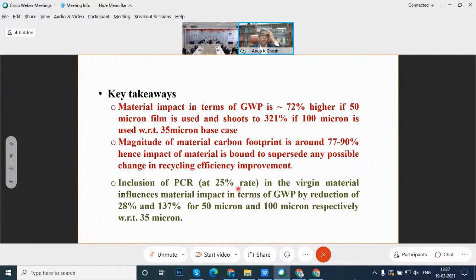We went back and we put 25% of the recyclate back in as a virgin material replacement, which is becoming the norm, that by 2023 we should have 20 to 25% PCR back into the making of the bottle, making of the container, making of the laminate tube, as a replacement of the virgin material. And you can see that by bringing 25%, we are reducing global warming potential by 28% and 137% for 50 micron and 100 micron. So if we have to use 100 micron, we must think of this PCR coming back, and that is reducing 137%.